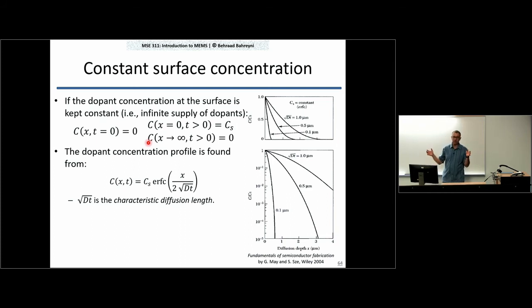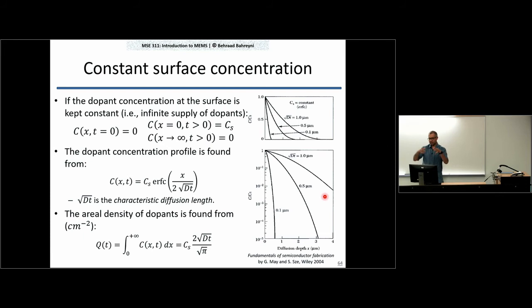So if you do the doping for 1 hour, t is in seconds actually, and at a given temperature, you can calculate D, the diffusion coefficient, given the time of doping. You can calculate square root Dt, the characteristic diffusion length, and you can figure out the concentration of your dopants at any depth from the surface. So you see the profile as shown here, the concentration normalized to Cs. At the surface you have 1, and it just keeps dropping as you go deeper and deeper into the substrate. And obviously the longer you wait, the more dopants you will have in the substrate. So what is going to happen is that because you're providing an infinite number of dopants, the longer you wait for your dopant, you get more and more of these dopants into the substrate.